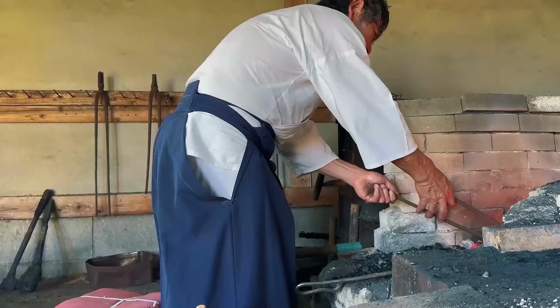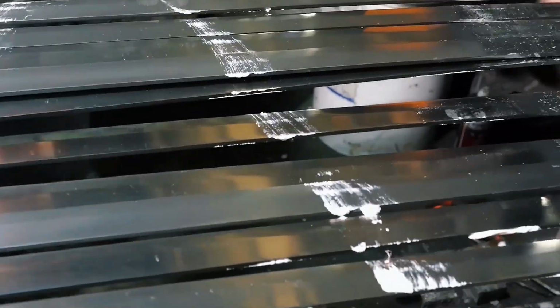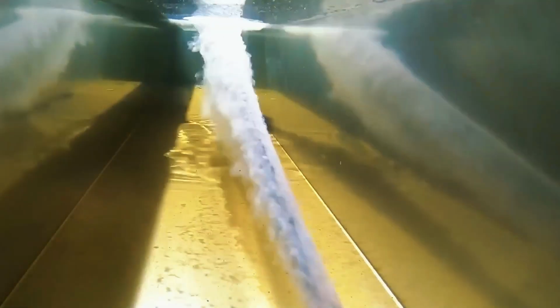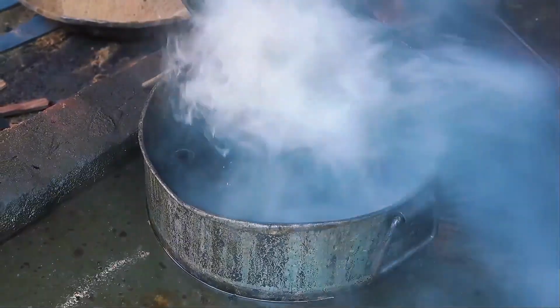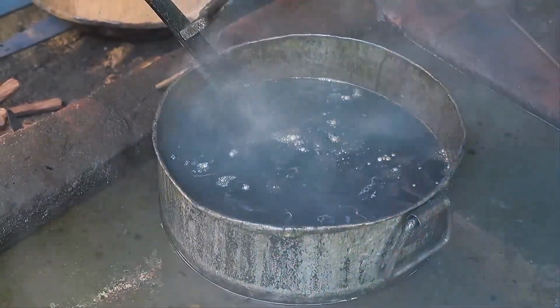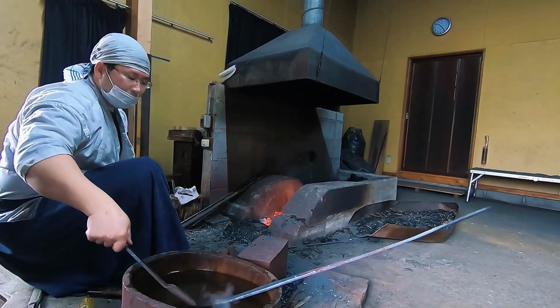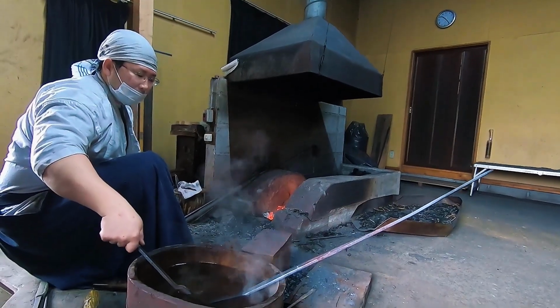Too cool and the transformation won't complete. Too hot and the steel burns. When the color is perfect, a specific shade of cherry red, he has seconds to act. He lifts the blade and plunges it edge first into water. In less than 2 seconds, the steel drops from 800 degrees to 20 degrees, one of the most violent thermal shocks any material can endure.